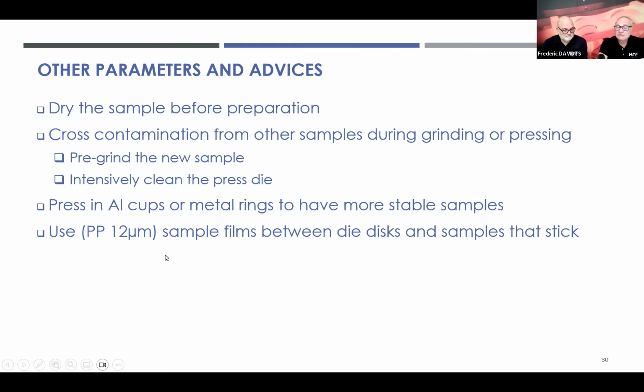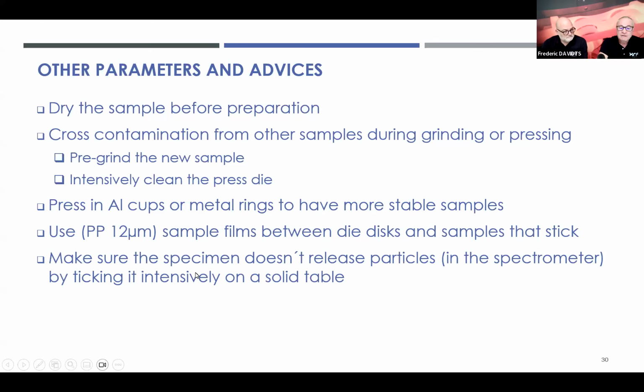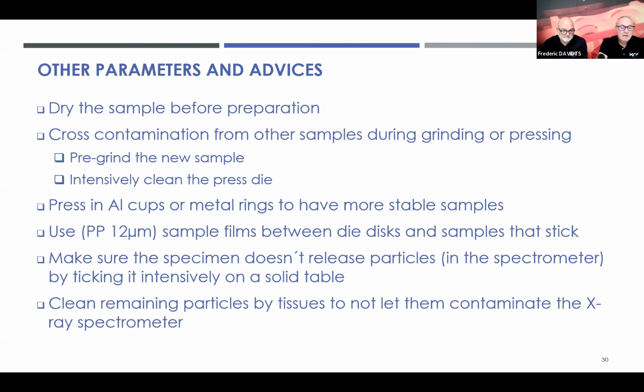And eventually you can use a sample film to put in between the powder and the die discs, such that it does not stick to the die. Generally this is a polypropylene 12 micrometer film that we are using. Always make sure that the specimen doesn't release particles in the spectrometer, of course, because it can contaminate your spectrometer, and costs may run high when you have a contamination. And always clean remaining particles eventually by using a tissue to not contaminate the X-ray spectrometer.